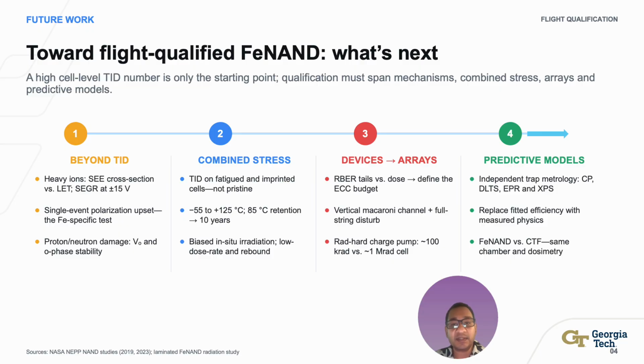The first workstream is single event testing. Heavy ions can deposit charge locally, trigger latch-up in peripheral CMOS, or create destructive rupture of the device under high electric field. We also need to determine whether a particle can nucleate a local polarization reversal, a failure mode unique to ferroelectrics. The second workstream is combined stress. Real cells arrive in orbit after fabrication, cycling, imprinting, and aging. Irradiation must be performed under bias across mission temperatures, followed by accelerated retention.